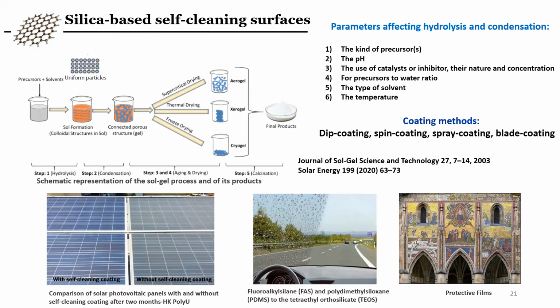Organosilanes are added to a specific solvent, which is commonly water and ethanol. Hydrolysis and condensation happen, and depending on the way you dry it, you can obtain aerogel, xerogel, cryogel, or even nanoparticles. The parameters affecting hydrolysis and condensation are the pH, the type of precursor you use, the ratio of the water to the precursors, temperature, and the type of solvent.